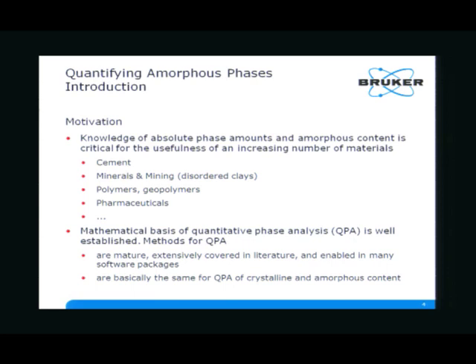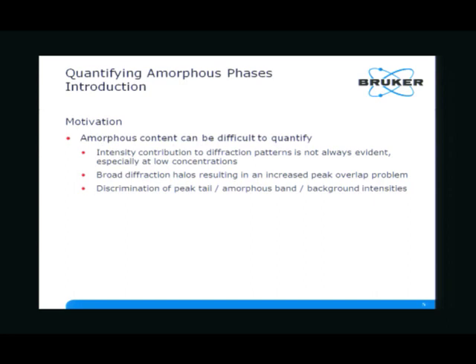Unfortunately, the basics are the same for phase analysis of crystalline and amorphous content. As we certainly all know, amorphous content can sometimes be extremely difficult to quantify. The intensity contribution of diffraction patterns is not always evident, particularly if we're dealing with low concentrations. We have broad diffraction halos resulting in increased peak overlap, which is one of the really major issues. It's difficult to discriminate between peak tails, amorphous bands, and background intensities.